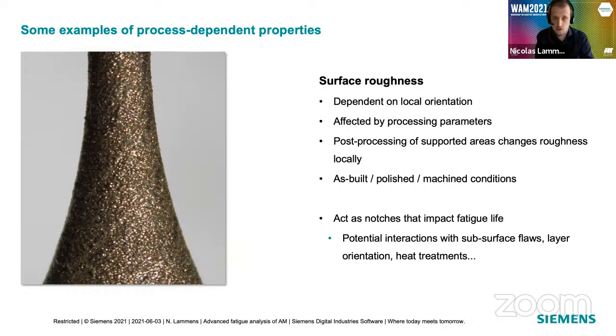Also, the post-processing that you use will affect the surface roughness. And while in itself it's already difficult to work with, all the surface roughness changes act as notches for the fatigue life. So they are important to know so that we can properly compensate for their contribution. And then again, in additive manufacturing, you have this additional complexity that surface roughness you should not consider just as a separate property, but actually it's going to interact with other properties as well. We all know that printing a perfect part in additive manufacturing with 0 defects is almost impossible. So if you have this surface roughness and you have a porosity that is just below the surface, it could actually be that the two are going to start to interact with each other and that they have a combined effect on the fatigue life. So that's also something to consider.